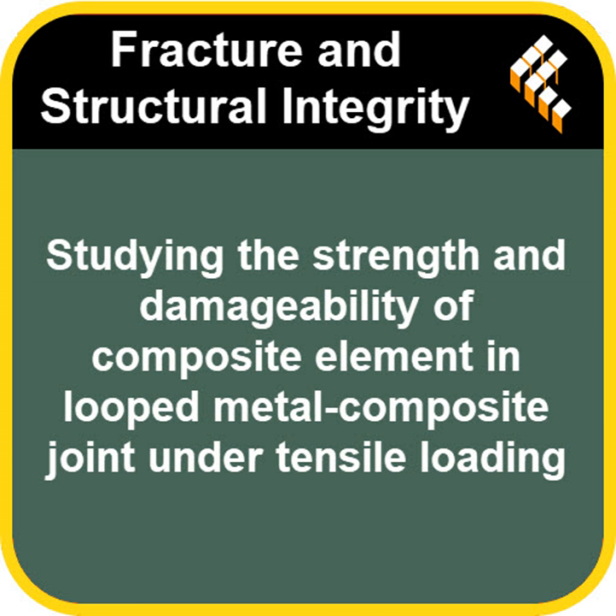And what's more, some of the initial fuzzy spots, the inhomogeneities they saw as light strokes in the images, actually disappeared after the 200 kN unload. Defects disappearing and shifting. Yeah. That's really counterintuitive. What's causing that? It's not just breaking down, is it? No, it seems to be something else entirely.